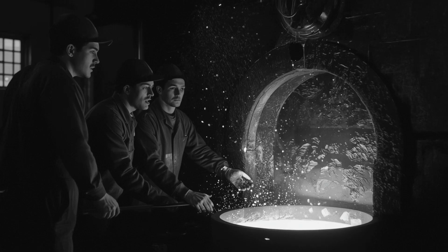By Wednesday, the phenomenon had attracted attention beyond the foundry floor. Mill engineers arrived with notebooks and instruments. They took systematic temperature readings using contact thermometers at marked intervals around the circumference and height of the casing. The data confirmed what the workers already knew. The outer shell maintained temperatures between 120 and 150 degrees Fahrenheit over most of its surface, with hot spots near the hearth reaching 170 degrees. For a furnace 3 days into a cold shutdown, these numbers were inexplicable.